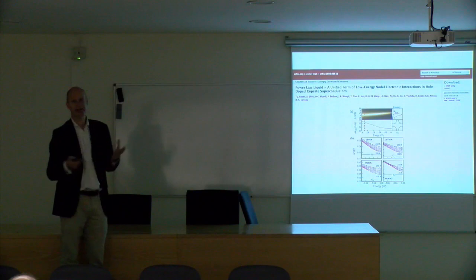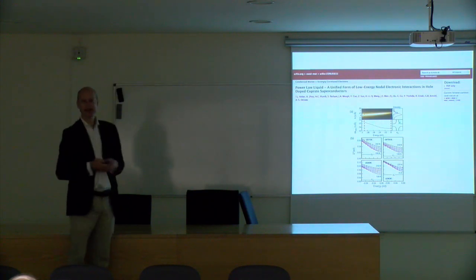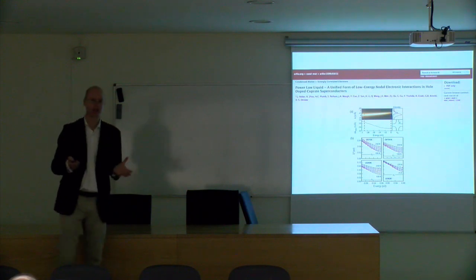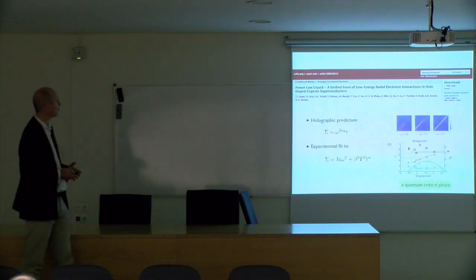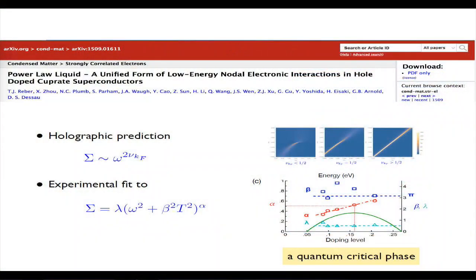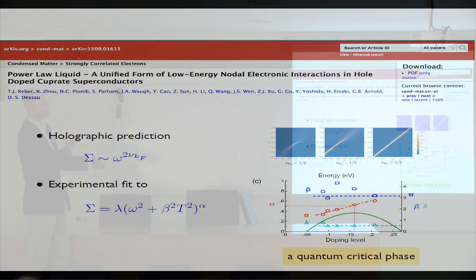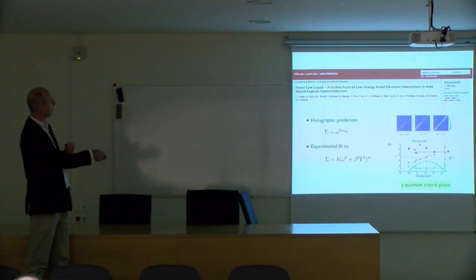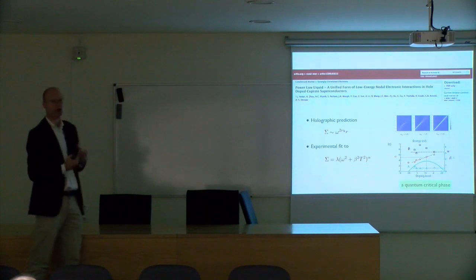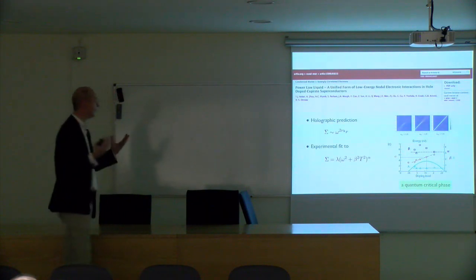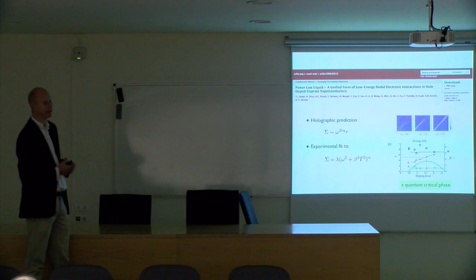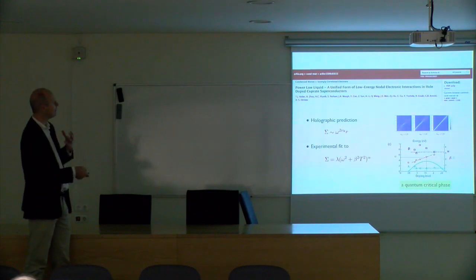Now, when they tried to match, theoretically, what these curves look like, they found that their ordinary metallic results did not match. They had no idea that there were these crazy guys trying to match string theory to strange metals, so they just came up with a phenomenological formula that matched their data. And this is the formula that they came up with that matched their data best. Look, it is precisely this formula when you make the temperature very, very small. In fact, even the alpha is exactly this nu kf that we and many other people that worked on this predicted in 2009.